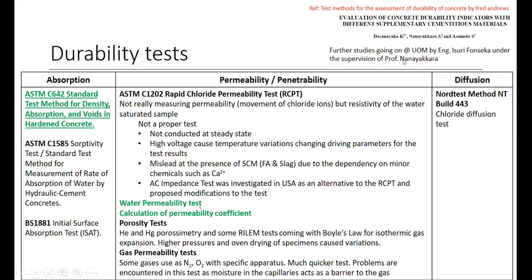We have published on this, and further studies are also being done at the University of Moratuwa by Engineer Isuri with the supervision of Professor Nanayakkara. What we have identified is that since this test is not conducted at steady state, it's just a 6-hour test with a very high voltage of 60 volts, that can cause variation in the temperature, changing the driving parameters of the test results. And it could mislead in the presence of fly ash or slag due to the dependency on minor chemicals such as calcium. So you could get an idea about OPC by utilizing this, yes. But if you're utilizing fly ash or slag, it will not deliver the real picture in terms of durability.